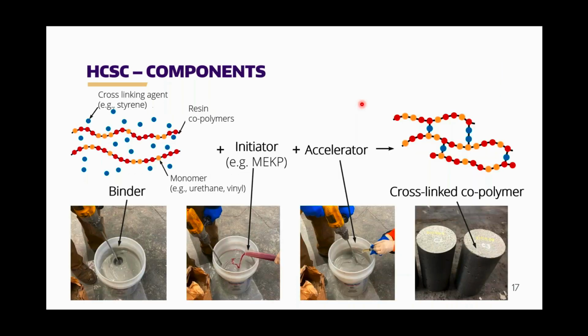So what does this look like in terms of the chemistry? So the binder comes pre-packaged with your resin copolymers and your cross-linking agent. That's a convenient way to package this material because you can mix it in different components on site. So you add to that binder an initiator, in this case a methyl ethyl ketone peroxide. That's what starts the cross-linking reaction. You can also add an accelerator at different dosages to control the speed of that cross-linking reaction. And at the end of the day, you have a cross-linked copolymer, which is binding the aggregate and fibers together.